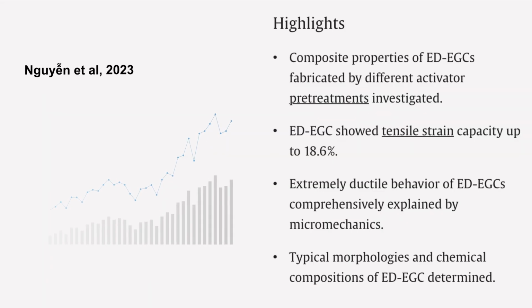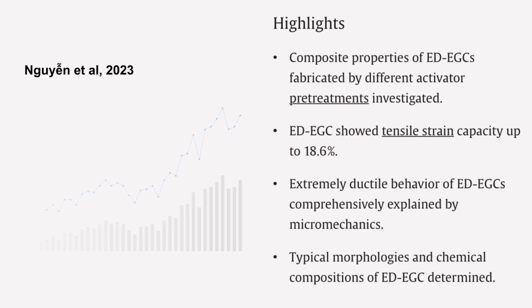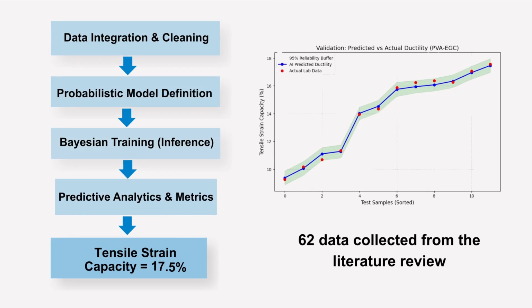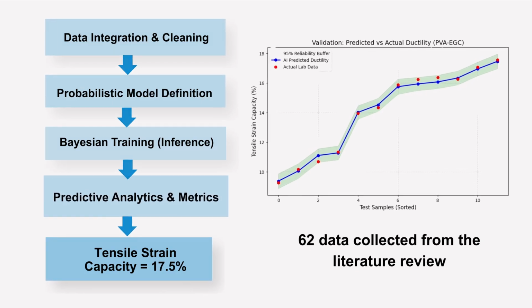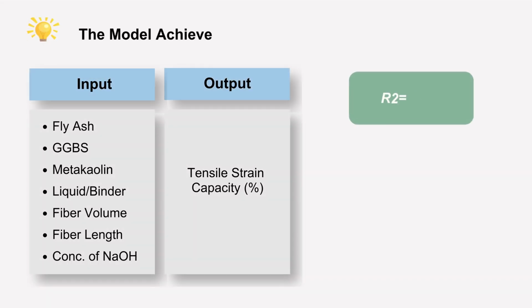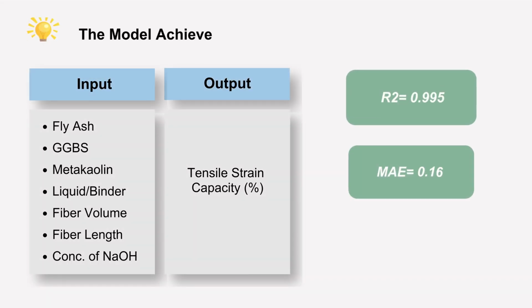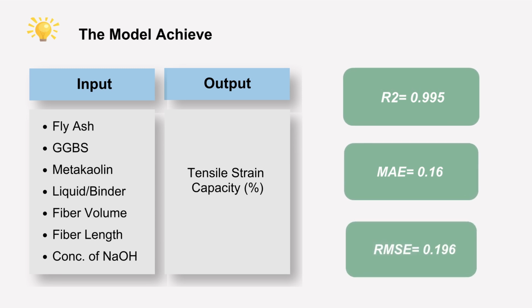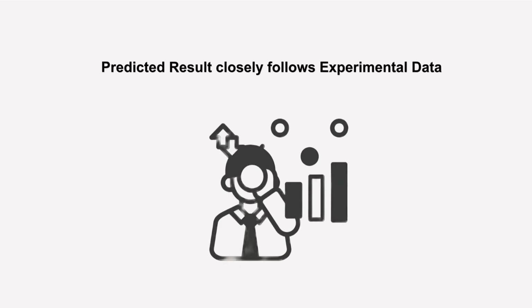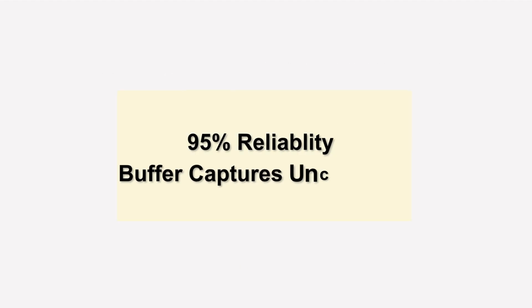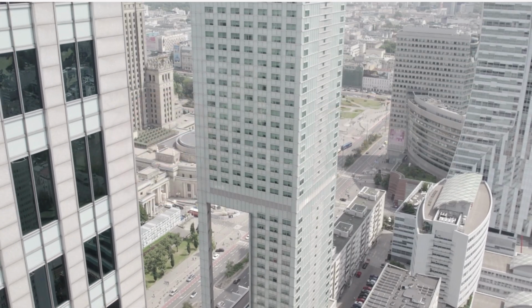Using ML, we used a BNN model to predict the tensile ductility of the PVA EGC composite. Experimentally, the tensile strain capacity reached 18%, while the model predicted around 17.5%, only about a 2.8% difference, showing excellent agreement. The model achieved excellent performance with R-squared 0.995, MAE 0.16, and RMSE 0.196, confirming high accuracy. In the validation plot, predicted results closely follow experimental data, and the 95% reliability buffer captures uncertainty, making the model both accurate and reliable for safe structural design.